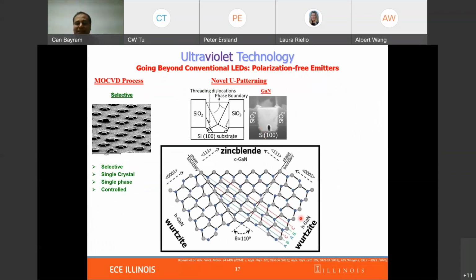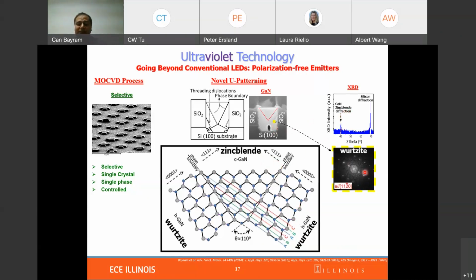Mainly, a six-fold symmetry and four-fold symmetry have a common direction. The Wurtzite 0001 direction is the same direction as the cubic 111 direction. One way to look into this is if you have a cube in your hand and you rotate it, you are going to see a hexagon. So this is what we are using. Basically, having two growth fronts coming together with the perfect angle is going to switch to cubic phase organically and naturally. So from the X-ray, we can see the emergence of cubic nitride, and from the selective area electron diffraction, we can prove that the incoming facets are Wurtzite and the resultant structure is zinc blende.